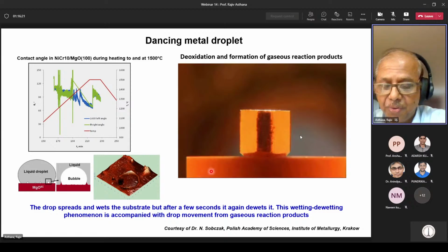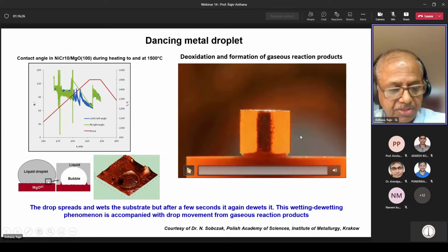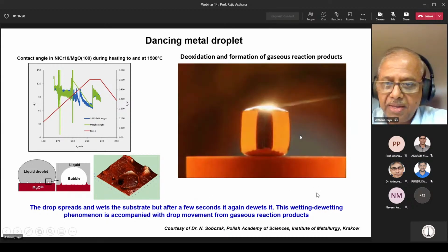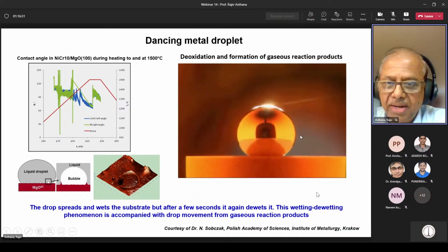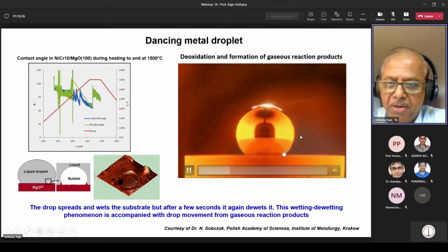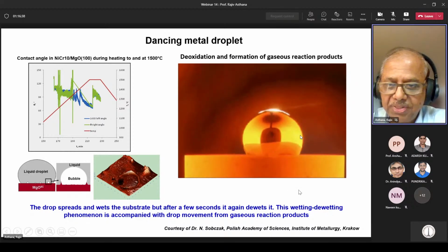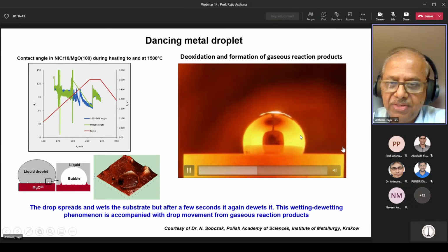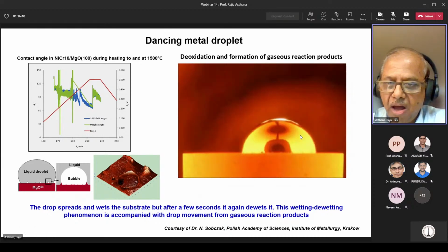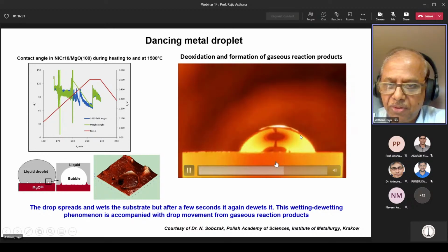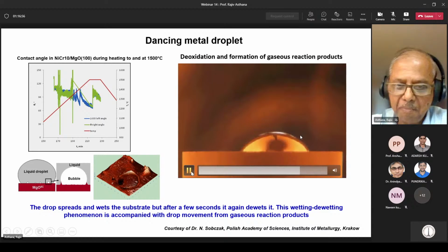So if you look at this video, you will see that there is wetting and de-wetting process taking place. And after some time, the droplets will begin to bounce and jump around during the heating process. And the reason for that is little gas formation here. So look at the bubble, the droplet, it is moving around on the surface.